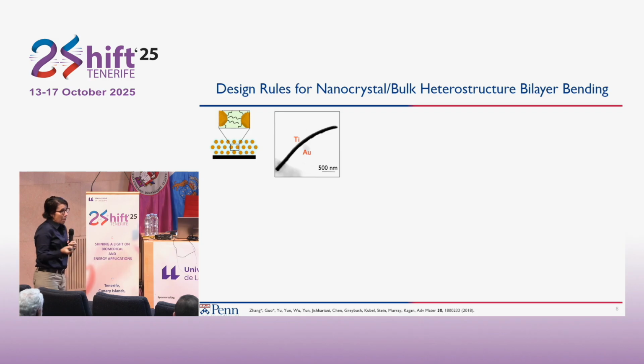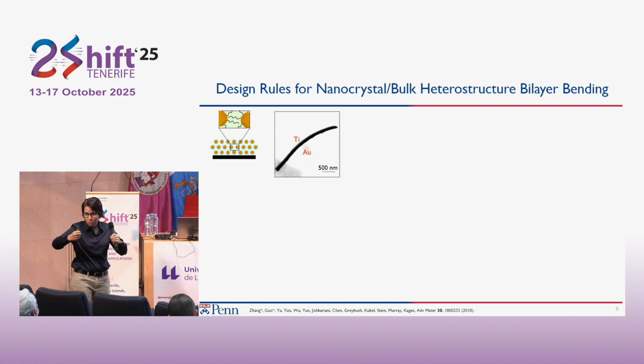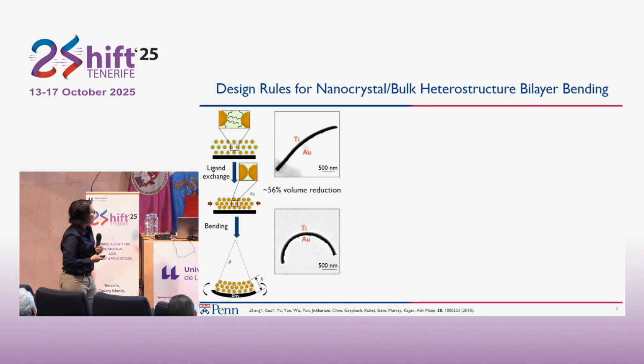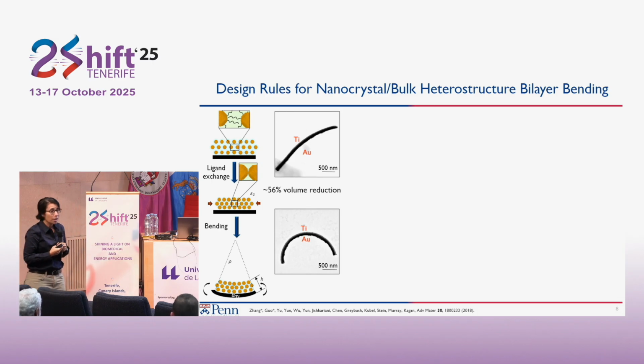Now if we take these structures and immerse them in a solution of this more compact ligand, what happens? All these particles want to come close together. That creates a compressive strain in this nanocrystal layer, and when it's juxtaposed with a bulk film, it creates a misfit strain at this interface. This causes all of these structures to curve in the direction of the nanocrystal film, because we have this compressive force here, and you can get these structures to fold. We then went and studied mechanics, not as mechanical engineers.